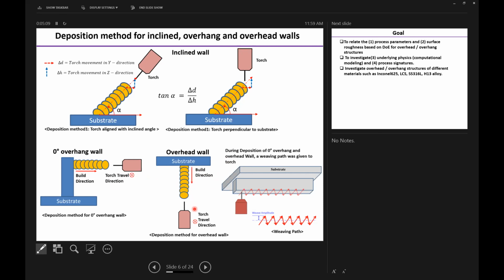Then for overhead walls, you can see the build direction is downward, which means we have to move the torch in the downward direction, and the molten metal is flowing down due to gravity. So while depositing this overhead wall, I use a weaving path. I have given the weaving path to the torch so that there is more surface area, and due to that there will be an increase in the capacity of the substrate, or the previously deposited layer, to hold the molten metal. So here, this is the weaving path.